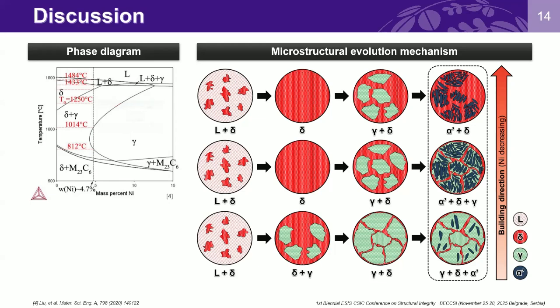In summary, with the gradual reduction of gamma stabilizer elements along the building direction, the retained austenite content decreased steadily, whereas the delta ferrite exhibits an upward increasing trend. Notably, the volume fraction of the alpha prime martensite first increased and then declined.